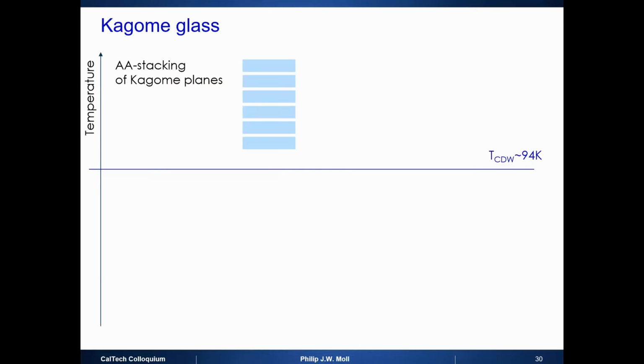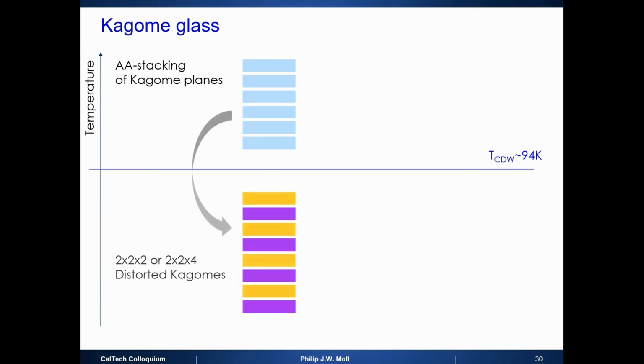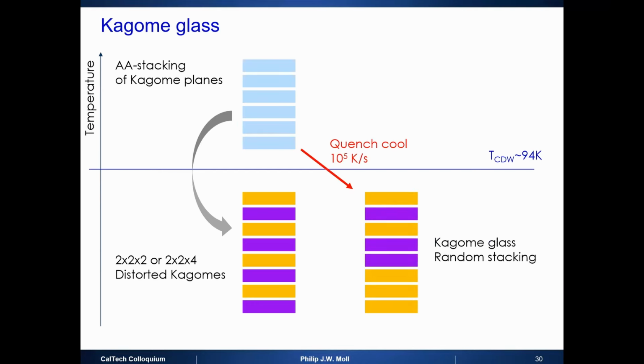Namely, think about how such a system goes through the charge density wave transition. So you put here temperature. At high temperature, this is a Kagome plane, well stacked. And now you cool it into the charge density wave state. Now it takes some order. There's actually debates whether or not this is 2 by 2 by 2, so AB stacking, or 2 by 2 by 4. It doesn't really matter. It finds its thing, and then you take the physical properties. What if you just blast that thing through the density wave transition?